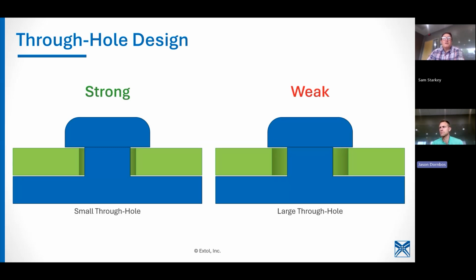If that through hole starts to get much larger, as you can see on the right, that's an exaggerated design, but you'd be surprised at some of the things that we've seen before. So as we design to that 35-ish percent diameter in our finished stake height versus your starting boss diameter, as you start to get larger, you could potentially get to a point where you're just hanging on to the hairy edges of that stake point. So really, we like to try and keep that tight.